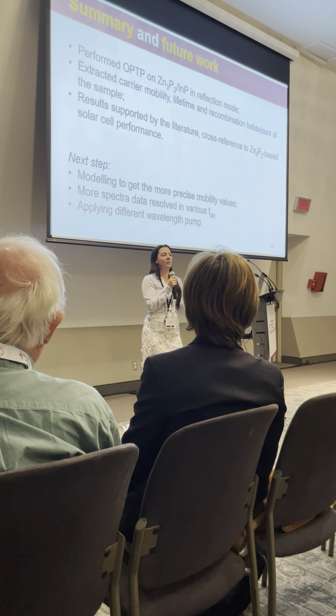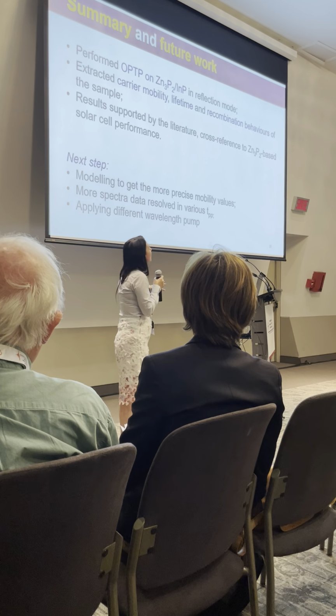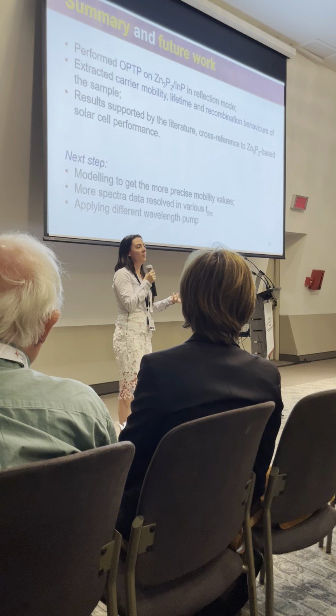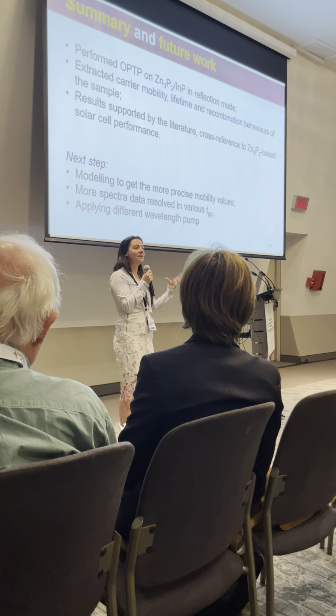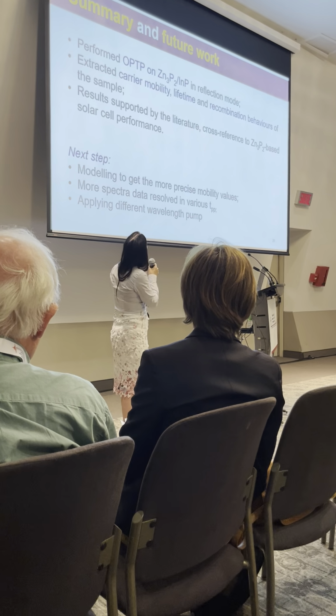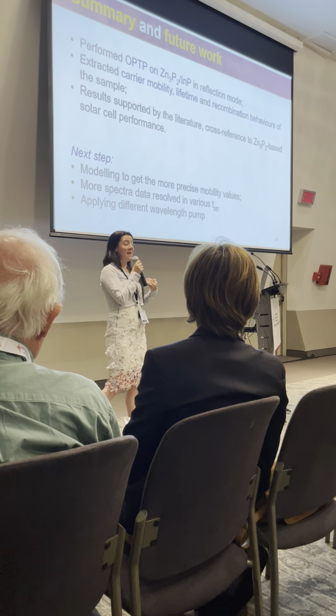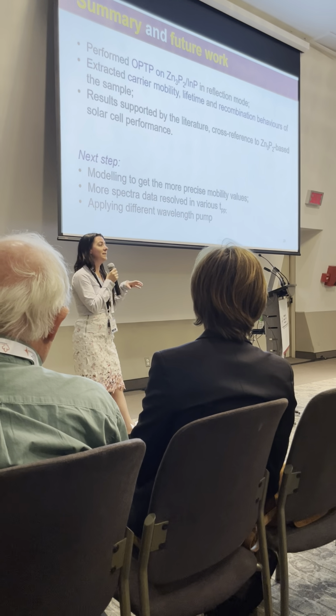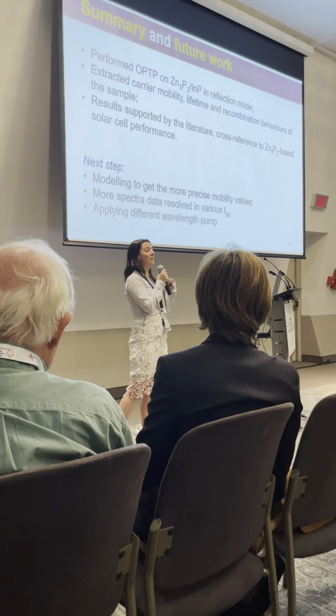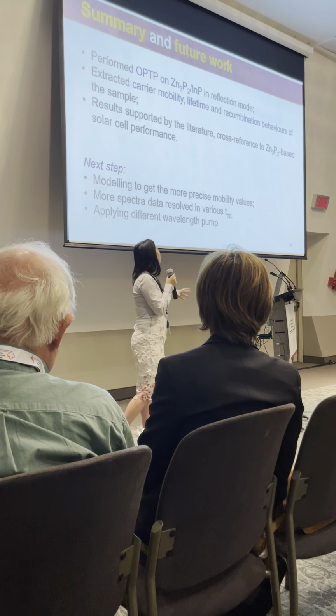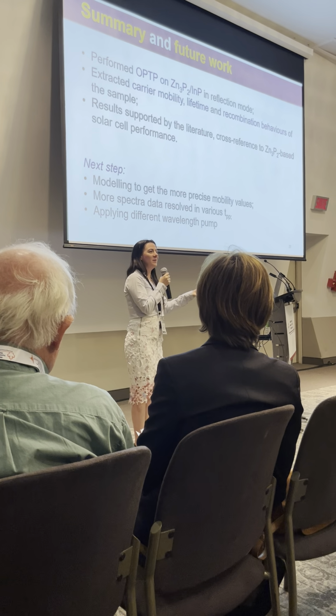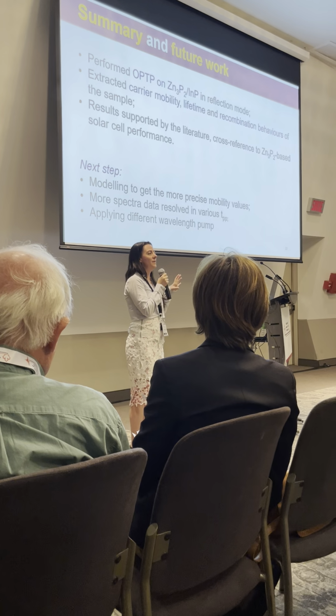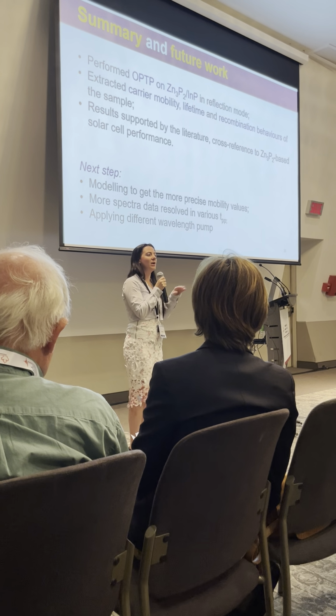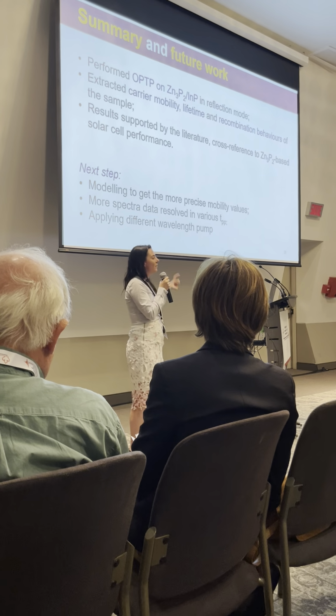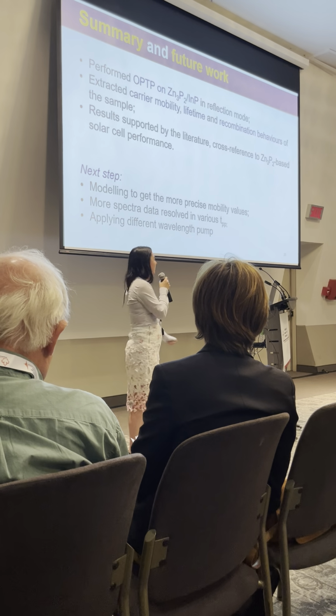And one of the strengths of this particular study for our collaborators was that we didn't have to change anything in the growth parameter. So we could look at it in situ on the substrate that they have grown. And the next future work for this is they're starting to grow on a graphene buffer layer. So we're hoping to look at those samples and use some of the knowledge that we've learned on the analysis side to look at them and try and do more full device measurements here on this thin film.